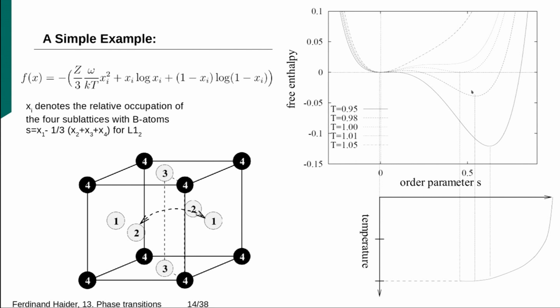And if you go lower, 2% below, you find this minimum here, still a minimum here - so the metastable disordered state. Here both have equal stability. Here you have a metastable ordered state. And only at temperature here at 5% below, you find this minimum here.